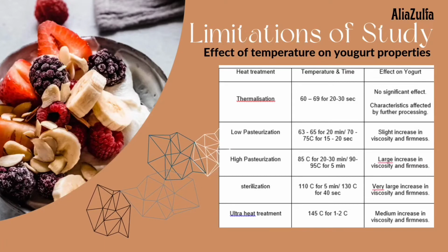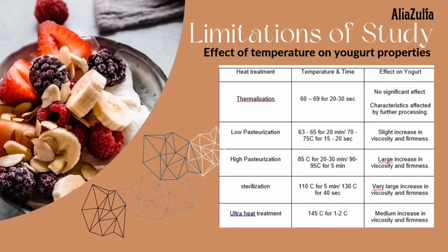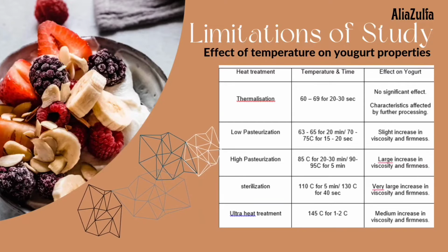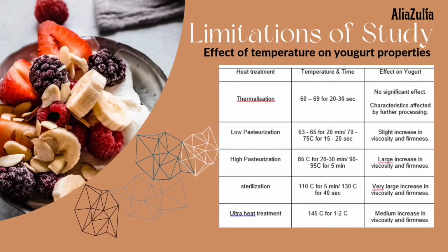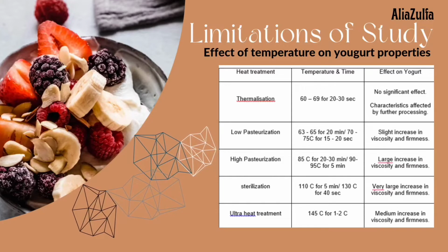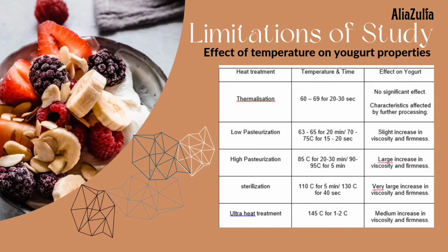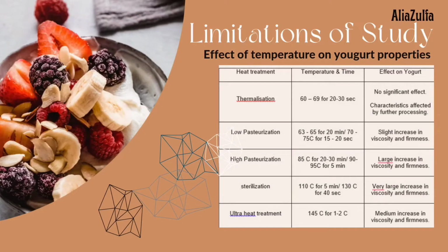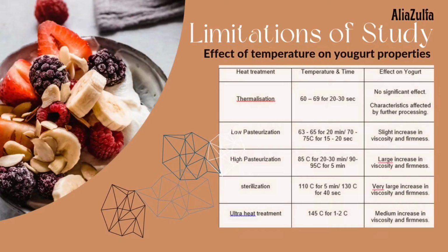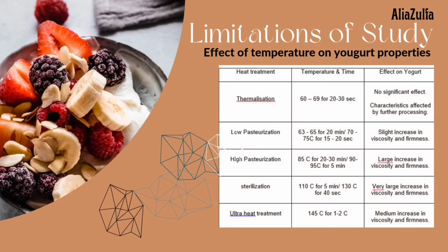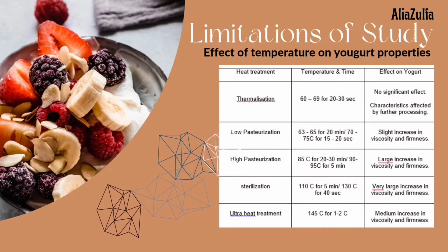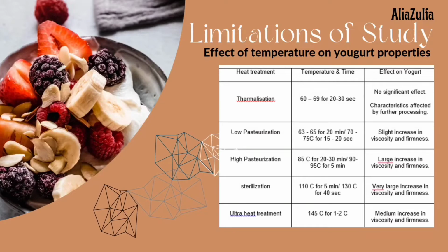Next, the heat treatment is high pasteurization. The temperature is 85 degrees Celsius for 20 to 30 minutes, or 90 to 95 degrees Celsius for 5 minutes. The effect on yogurt is a large increase in viscosity and firmness. And the second last is sterilization. The temperature is 110 Celsius for 5 minutes, or 130 Celsius for 40 seconds. The effect on yogurt is a very large increase in viscosity and firmness. Lastly, ultra heat treatment. The temperature is 145 Celsius for 1 to 2 seconds. The effect on yogurt is a medium increase in viscosity and firmness.